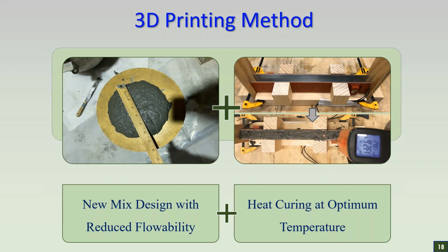For 3D printing applications, as ultra high performance concrete is a very flowable material, it becomes very difficult to perform 3D printing with the conventional ultra high performance concrete. So what we did here, we modified the mix design and reduced the flowability of the mix. On top of that, we introduced heat curing at an optimum temperature. The benefit of heat curing is that it reduces the open time of the UHPC, which gives an optimal window to work with the 3D printing of the material. It also increased the buildability of the printing material, which allows printing taller and wider sections.